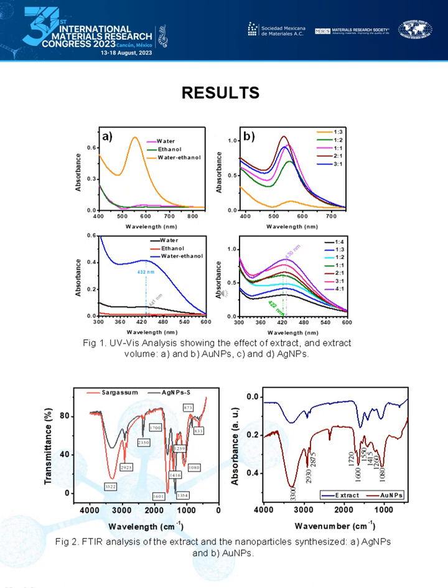On the other hand, the volumetric ratio between precursor salt and sargassum extract was evaluated. In this case, it's observed that as the extract increased, the absorption band corresponding to the nanoparticles increased too, indicating a higher concentration of nanoparticles, which is attributed to the greater presence of reducing agents from the extracts. It's important to note that the position of the band has no significant changes, indicating that the size and size distribution of the nanoparticles is similar in the samples.